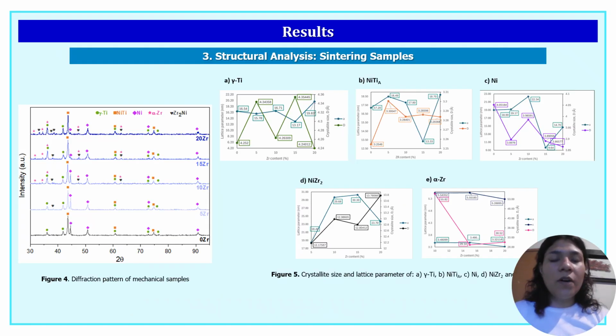In figure 4, we can also observe the X-ray diffraction patterns of sintered samples, showing the presence of gamma titanium, austenite, and pure nickel phases, along with the formation of the zirconium 2 nickel intermetallic in the 5 zirconium sample, and the stabilization of the alpha zirconium phase starting from the 10 zirconium sample.